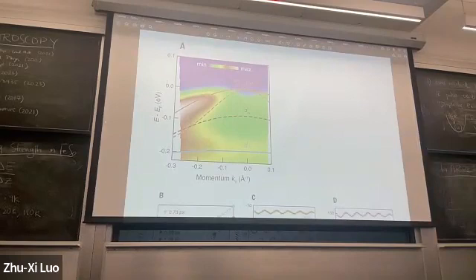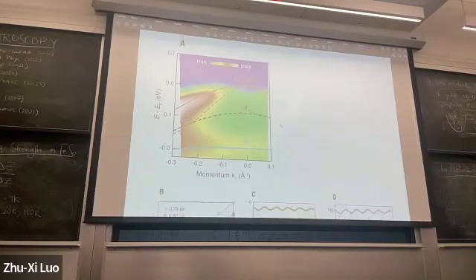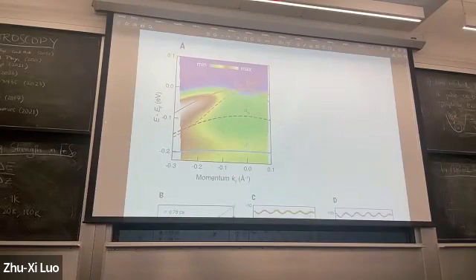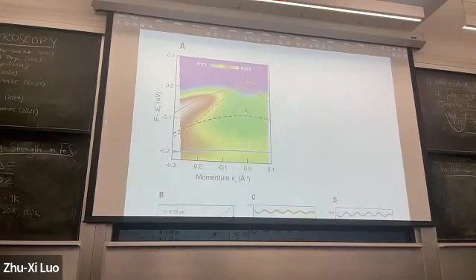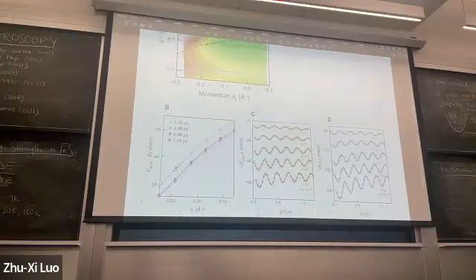So what's the white spot of green? So you're supposed to be able to extract those curves from the density plot? Well, the band structure is calculated, I think, by DFT. It's not necessarily extracted from this data. But what you can do is look at constant momentum slices, and you get some energy curve, and by fitting the peak of this, you can trace out what your band is. And that's what they're doing in this time series data as well.